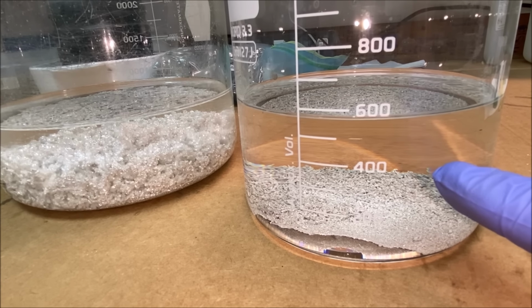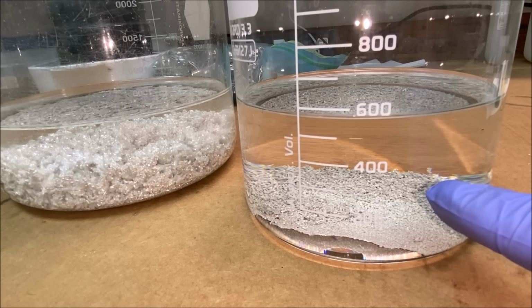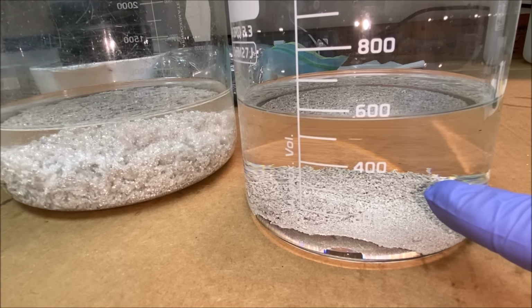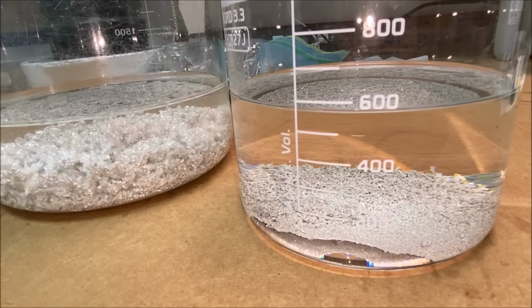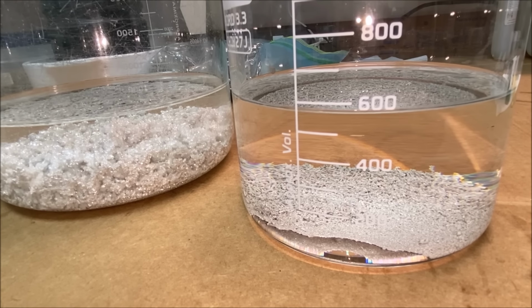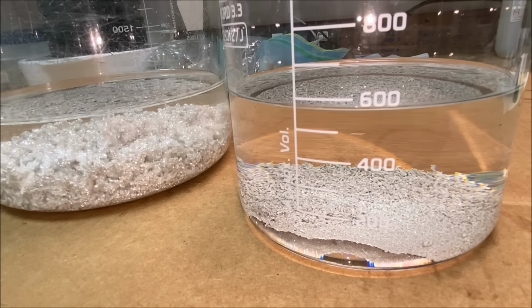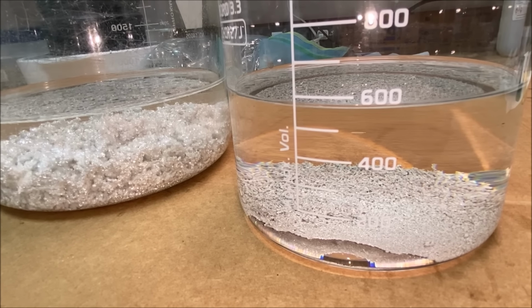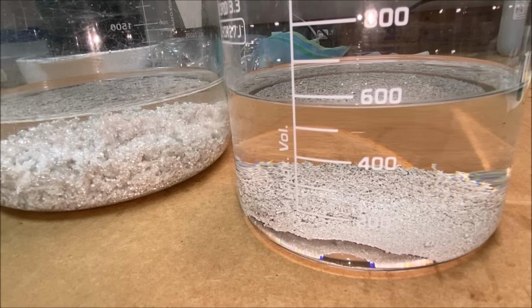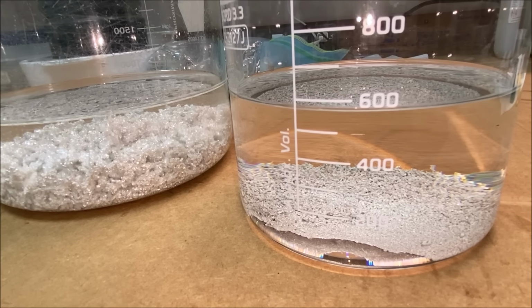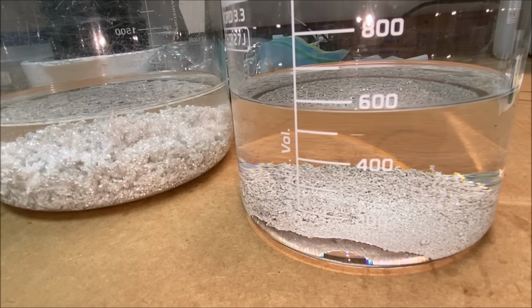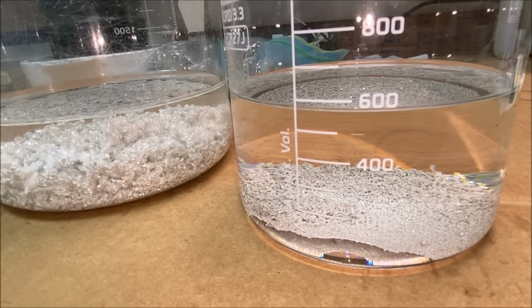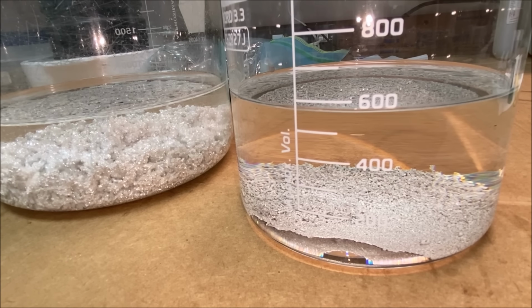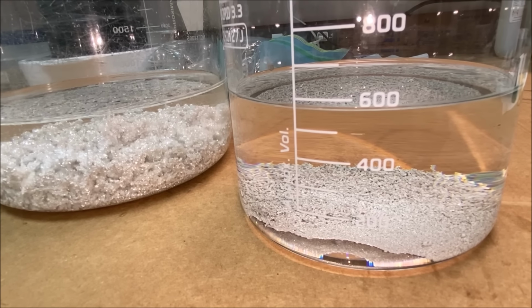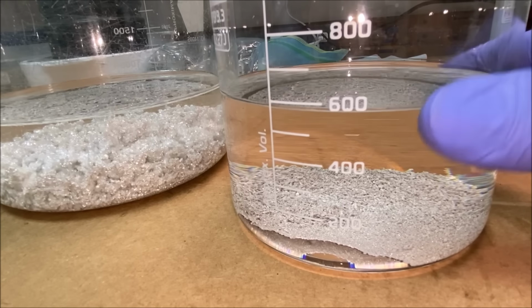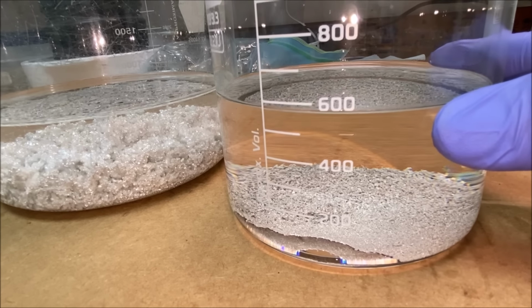We don't want a whole bunch of nitric acid in the electrolyte, because then it will have a tendency to dissolve the metals that get trapped in the anode filter basket. And then those metals, mostly palladium is what I'm worried about, can become dissolved, travel down through the electrolyte, and begin to plate out with the pure silver crystal. So this is what we're going to use for the electrolyte for the silver cell.